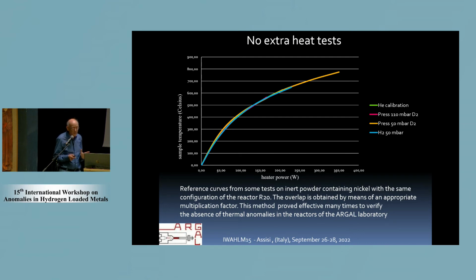To do the comparison, we can have two choices. One is to overlap the curves, because with different gas and different pressures, you cannot have exactly the overlap of the thermal measurements. So we need to use a multiplicating factor to overlap the curves, or we need to make the derivative of the curve just to see if we have an inflection during the experiments. The inflection of the curve means that you may have some extra heat production.